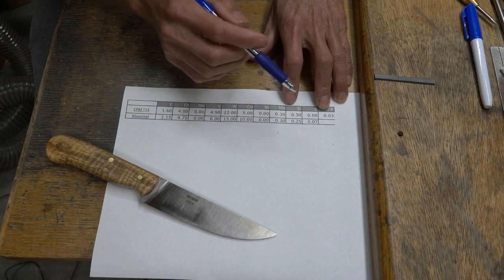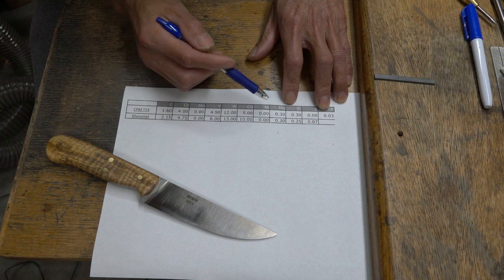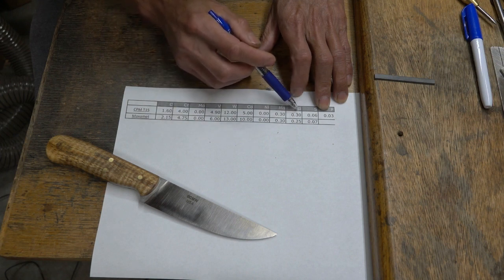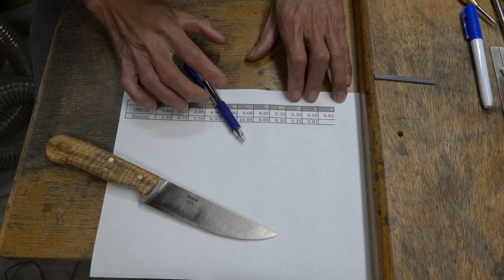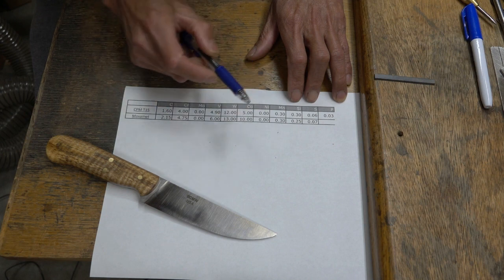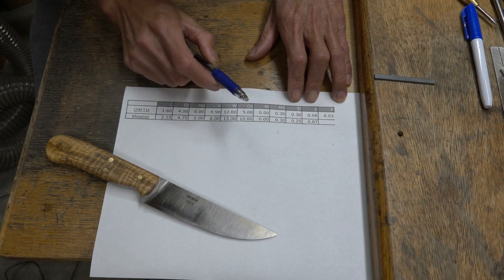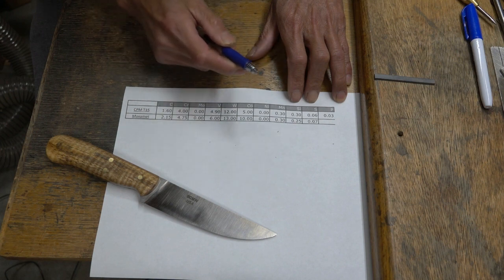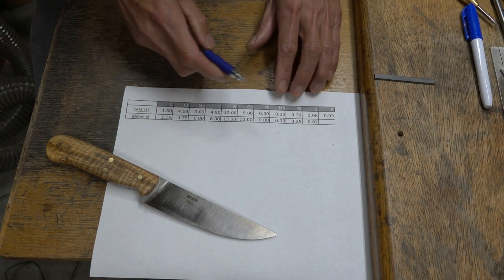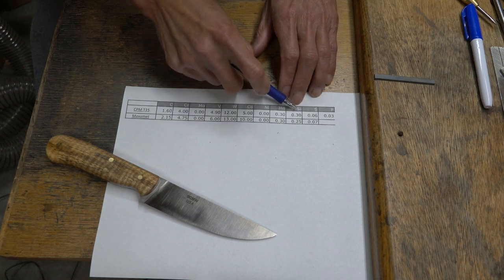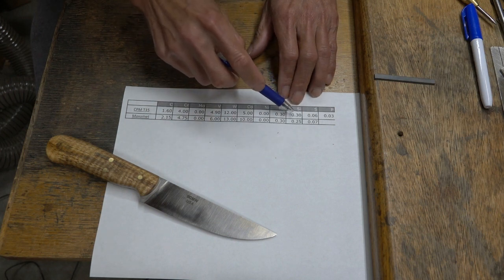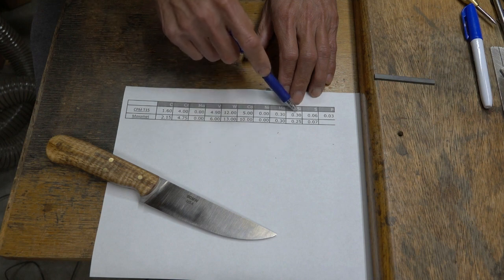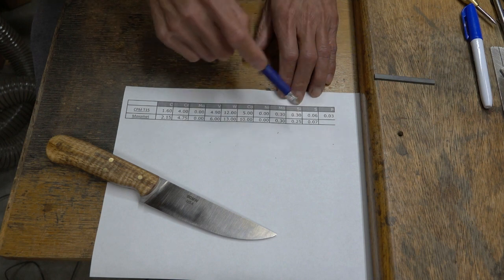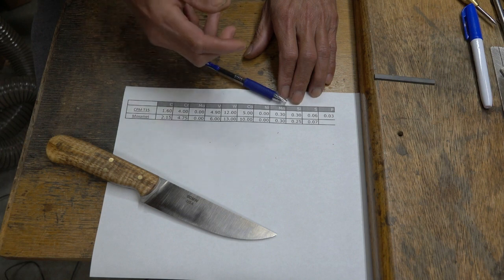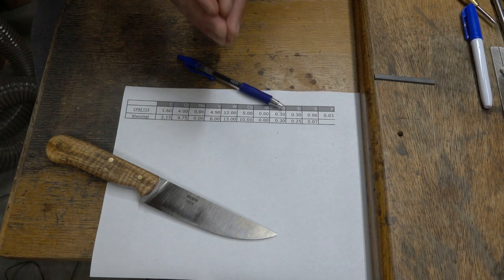I think the easiest correlation you can find: you look at the steel that has a lot of silicon, the higher the silicon it is, and now when you try to sharpen it to, say, a straight razor edge, something below 500 nanometer radius, now try to do that with a steel that has really high silicon content, let's say 0.5 and up. Then you will realize why I keep losing my keen edge. The smooth edge is not there.